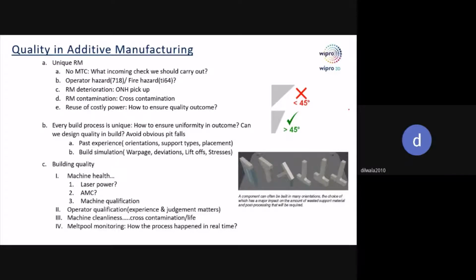Let me give you one example. We had a propeller part where the blade was planned to be finished in as-built condition itself. So to avoid any distortion, we provided additional supports so that we do not get much distortion on the blade. So in order to remove the supports, we had to do machining. This resulted in distortion on the blade profile after machining. As the stock was high, we ended up with the same issue for which we had provided support to avoid. So we need to be very cautious about where we are adding additional material and how much stock we are adding.